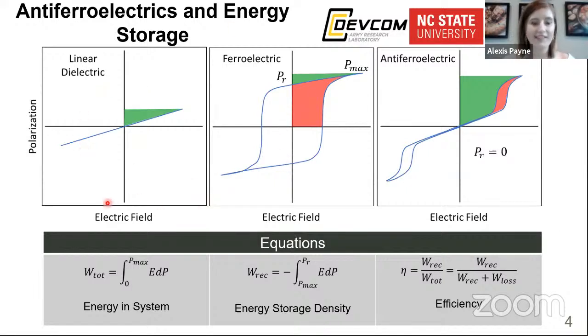And in front of you, you can see a 3-panel of polarization versus electric field loops. In the left-hand one, you can see a linear dielectric, in the middle, a ferroelectric, and the right-hand side, an antiferroelectric. So for the linear dielectric, you can see that as we increase the electric field being applied, we get an increase in the polarization. So as the electric field is being applied, more and more of those dipole moments orient in response to that electric field.